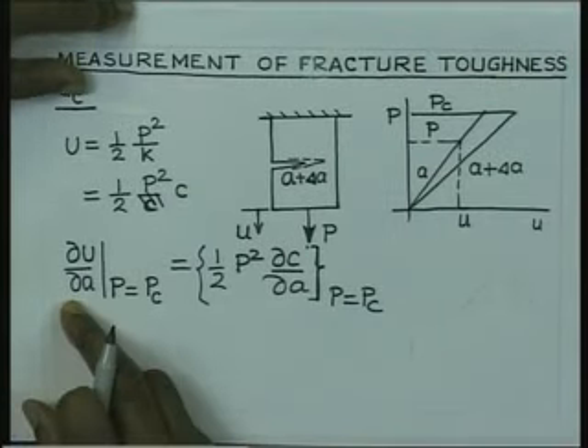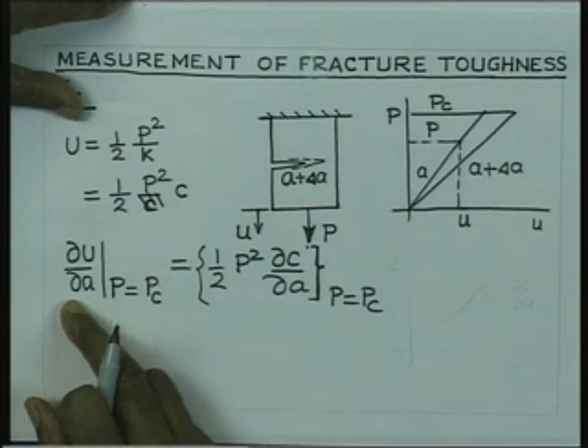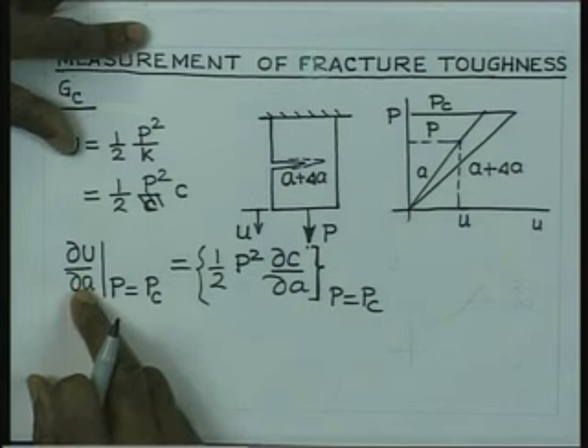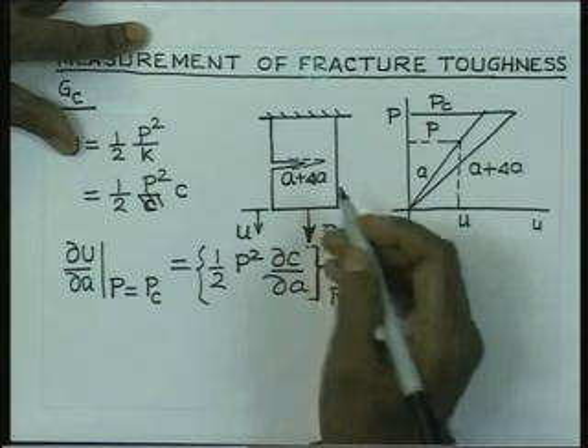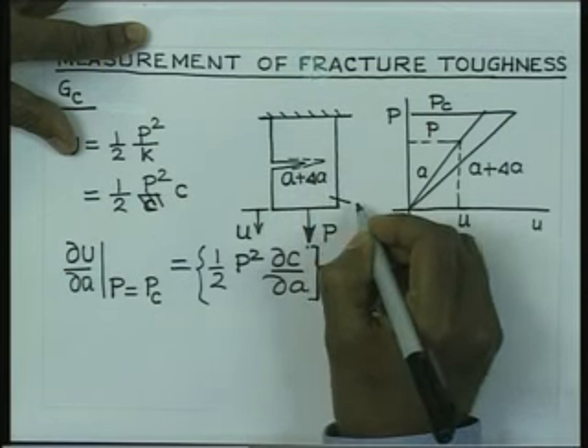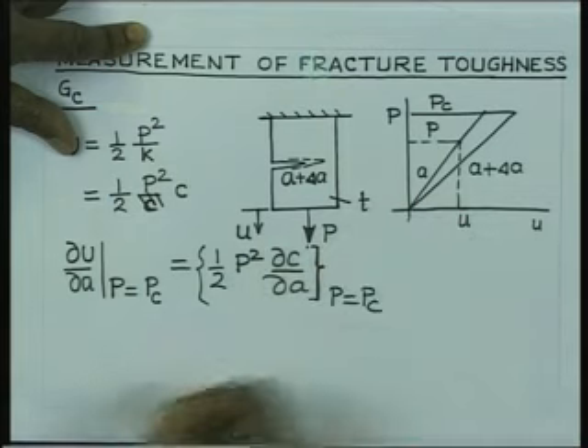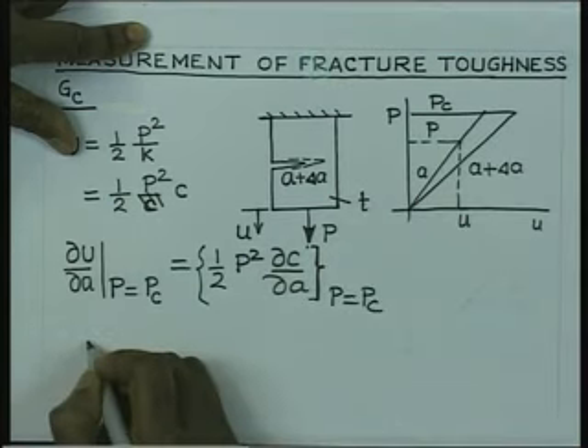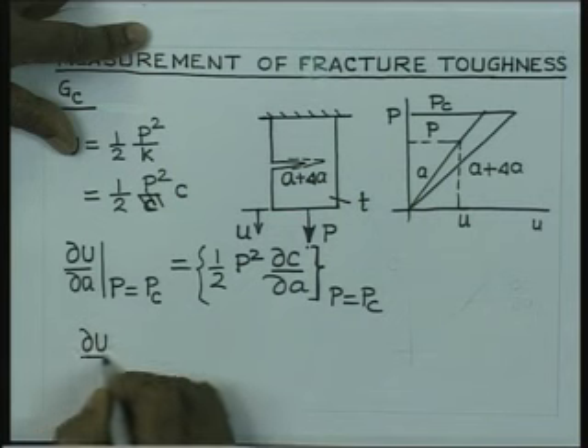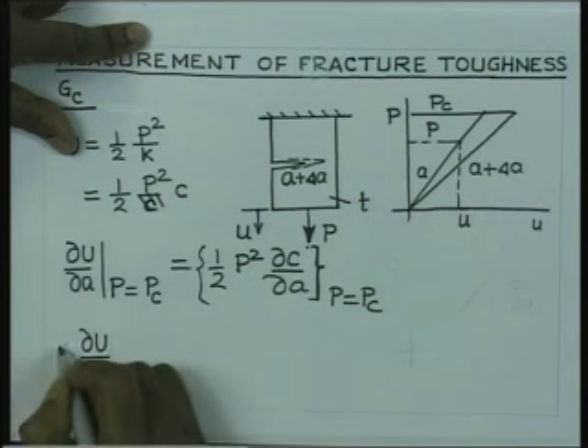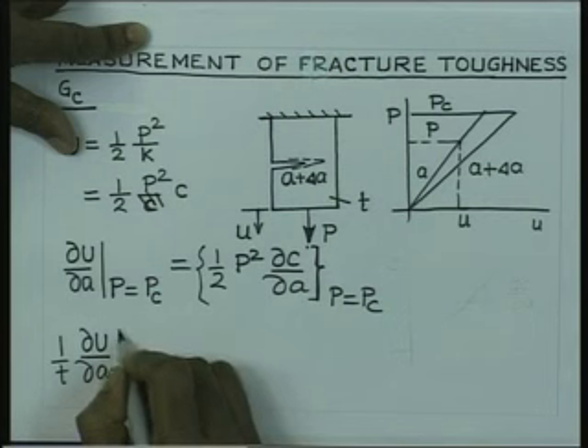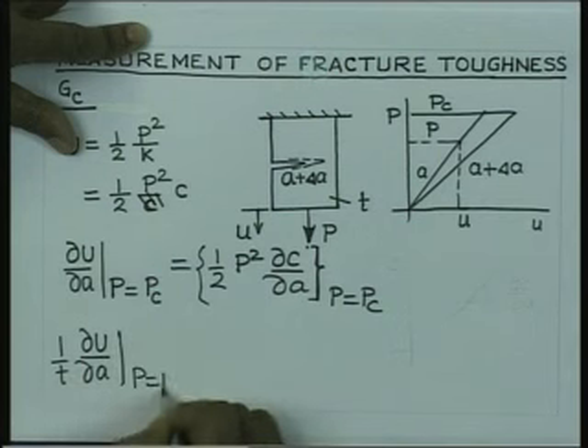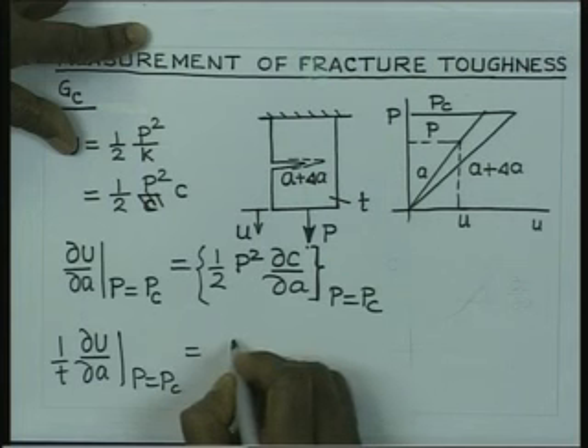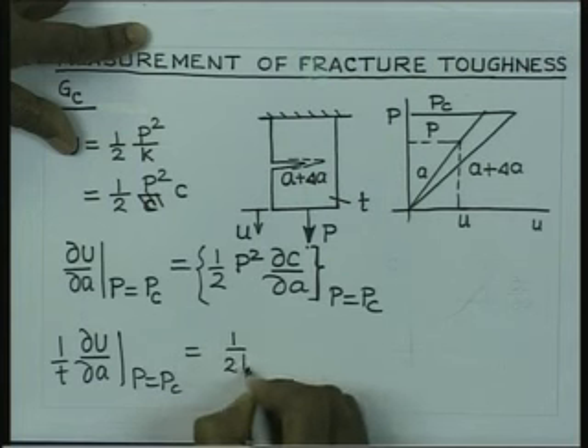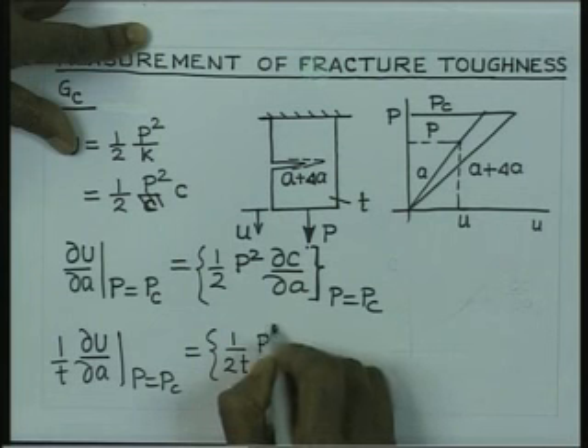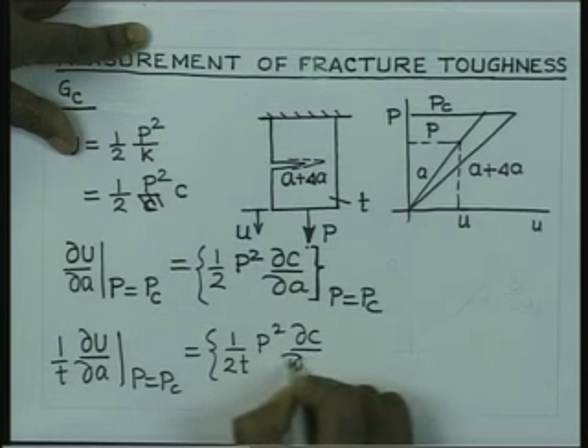So, this gives you the rate of strain energy release per unit crack extension, and when you have unit crack extension, if the thickness of this specimen is equal to T, then the energy release rate, 1 by T delta U by delta A at P equal to Pc, is given by 1 by 2 T P square delta C by delta A.